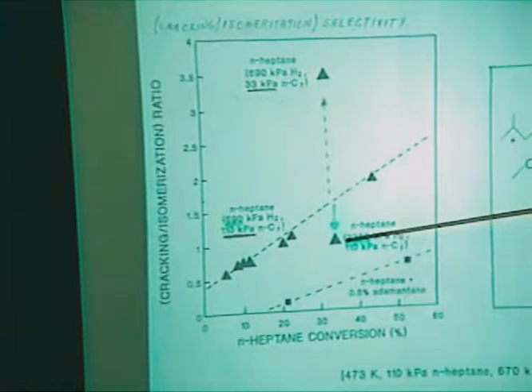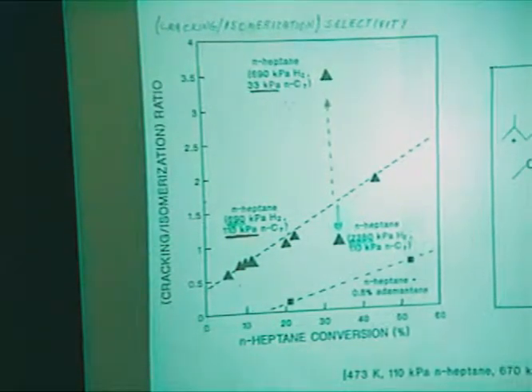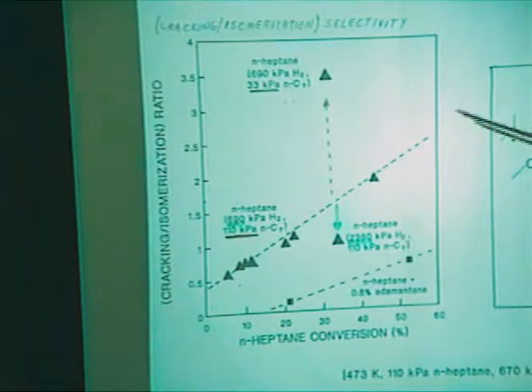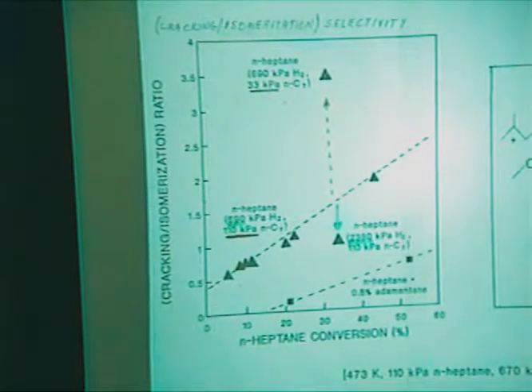Maybe the selectivity issue there is not clear, so let me look at it here. Remember, it depends on conversion. This is the cracking to isomerization ratio of the two rates, the selectivity to cracking for normal heptane as a function of conversion. This is the rate when you have 0.6%, one molecule for every 200 hydrocarbons of adamantane, and two things are clear. The selectivity to cracking has decreased dramatically, and also the intercept, wherever it may be, the intrinsic probability of cracking after one surface sojourn is no longer finite, but it's probably very near zero. So I have decreased the residence time of this species, I have gotten it off the surface more rapidly, and now they're not around long enough to do the undesirable side reaction.